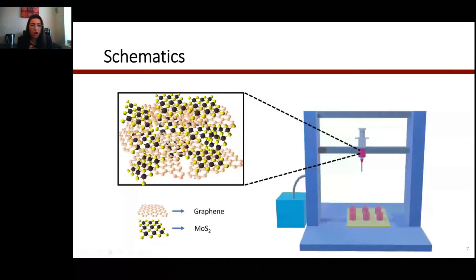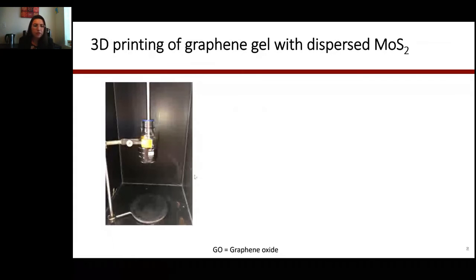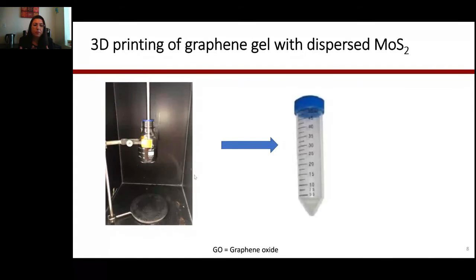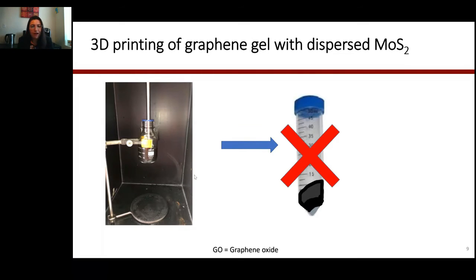And after that, we did lyophilization. The first part of the process was mixing graphene and MoS2. We used a tip sonicator that's been done a lot already. But the interesting thing is that what a lot of people do, especially for graphene gel, is supercentrifugation. Once we used graphene and MoS2, with the difference of density, we had phase separation, and that meant we couldn't use supercentrifugation anymore. So we had to find a different way to concentrate the solution and create the gel.